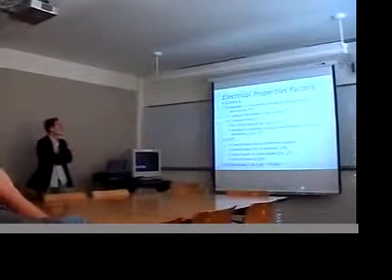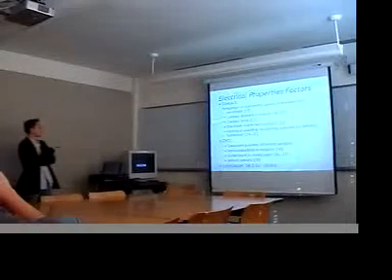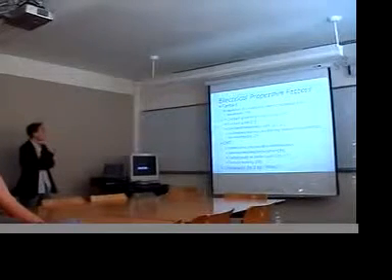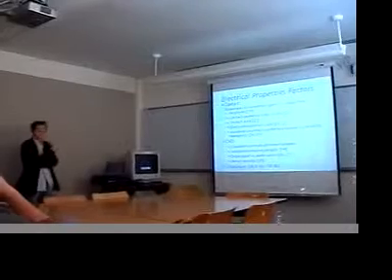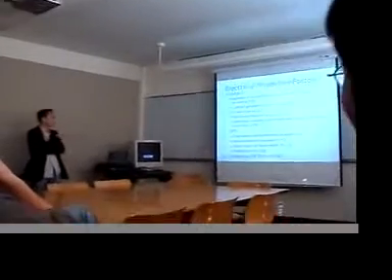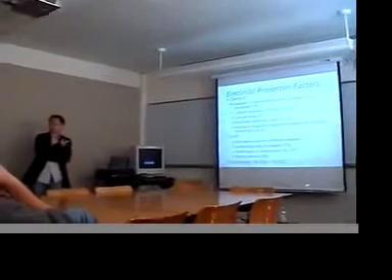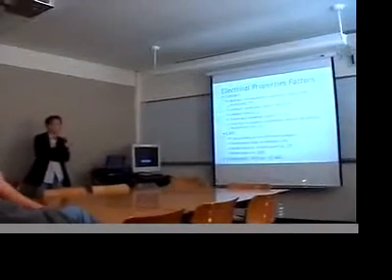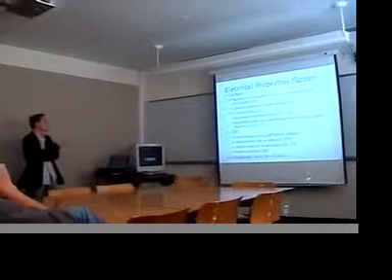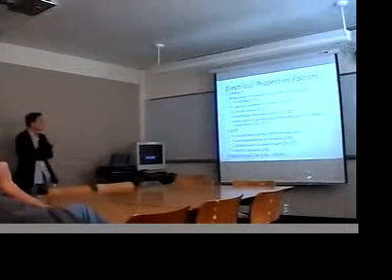Before I talk about the IV characteristics, I just want to go over many of the factors that can contribute to different measurements. At the contact level, the number of concentric layers that are in contact with the electrode matters a lot. There is a lot of dispute about whether most of the current goes through the outer layer, but there are also some papers that suggest that the inner layers also contribute a significant amount. The contact area and the contact geometry are also big factors.